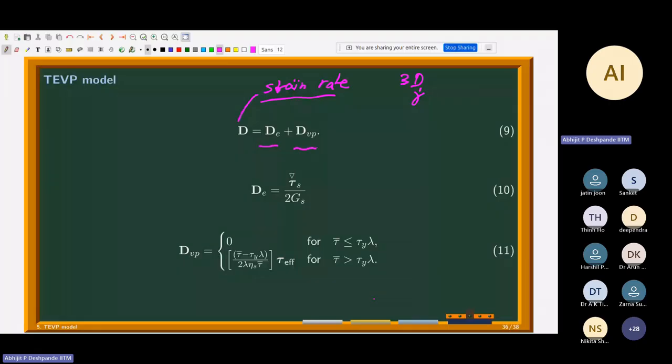One gives you the overall structural contribution, and it is called the elastic part. This is a model which is called neo-Hookean. If you read a little bit, it's basically for a network system. Given that the particles are forming agglomerates and networks, we get a neo-Hookean solid-like response from part of the system. And then the other part of the system is viscoplastic, and that depends on the overall value of stress in the material.